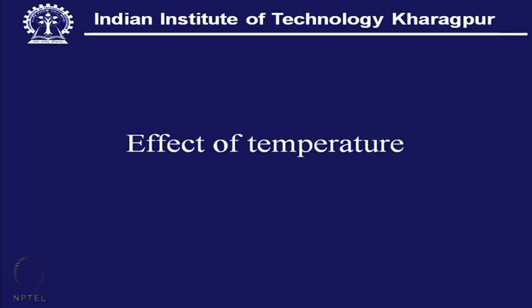Effect of temperature. We have mentioned that this is actually activated by temperature. Naturally, the growth rate will be quite high at higher temperature. However, one thing should also be taken into consideration: the limit of the CVD reactor and also the substrate of choice, which should not be affected by this high temperature.